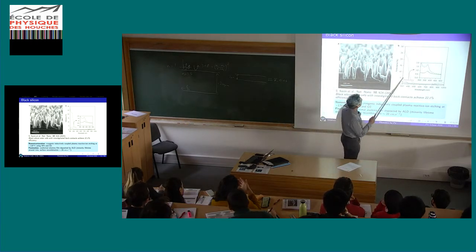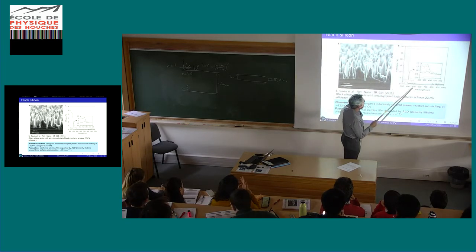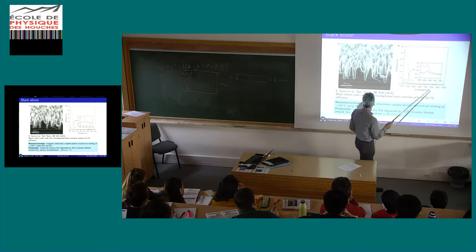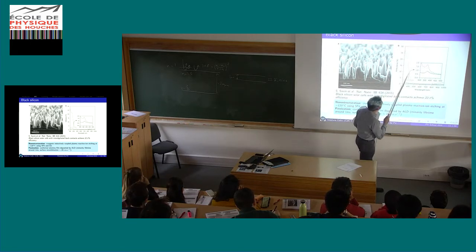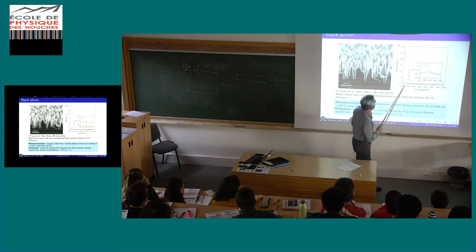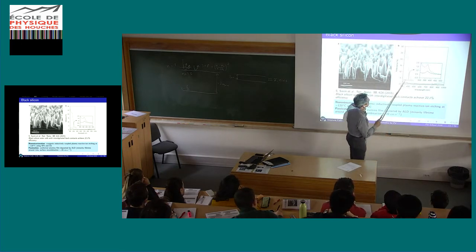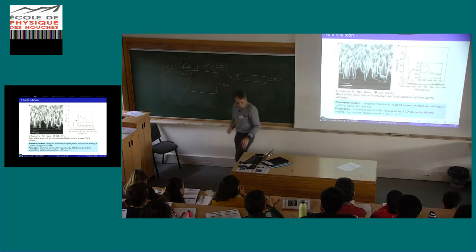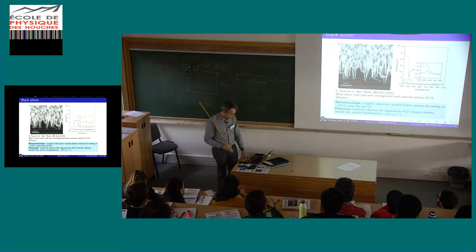So they measure the reflectance of this sample, and you can see a reference sample with a single, I think it's a single or bilayer, actually, I don't remember. Let's say conventional anti-reflection coating. And with this feature, the main advantage you can see here is that you don't have this increase of the reflectance at short wavelengths. So it works on a broad spectral range.